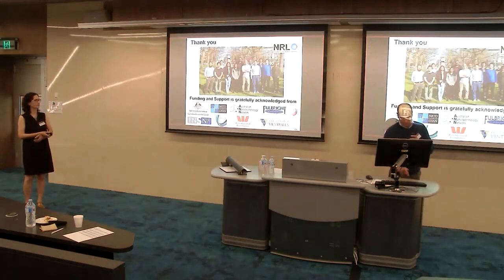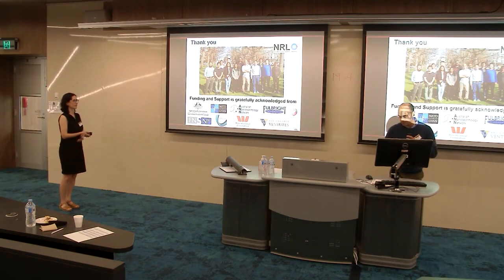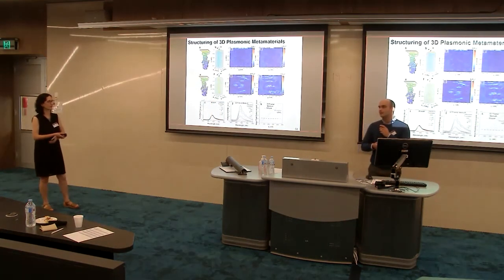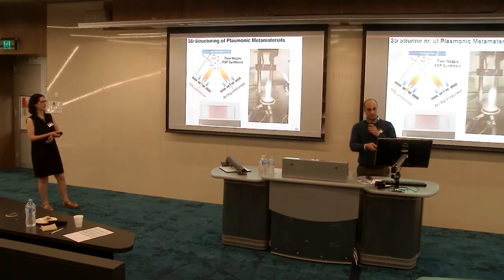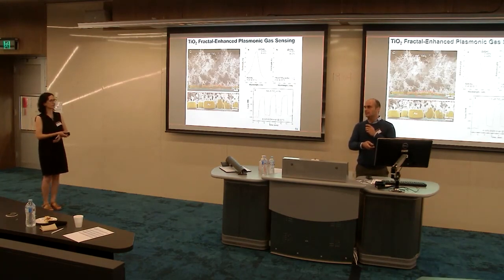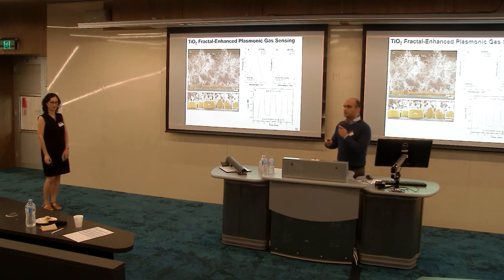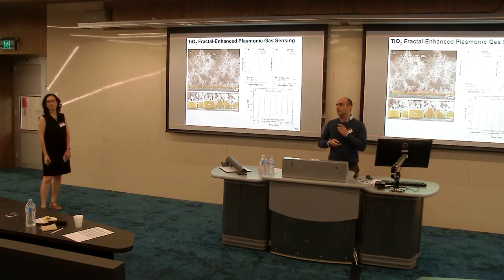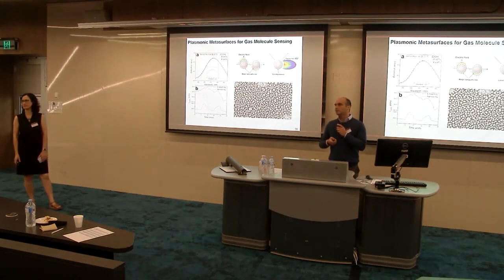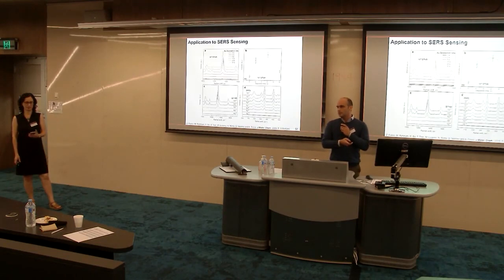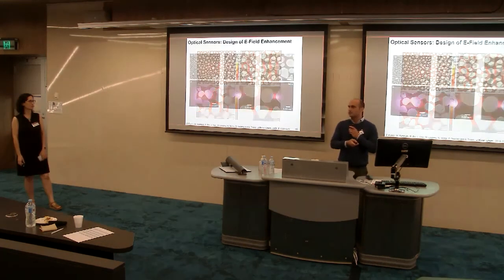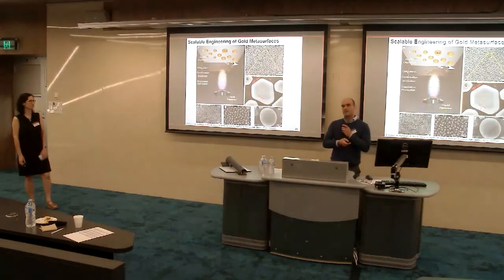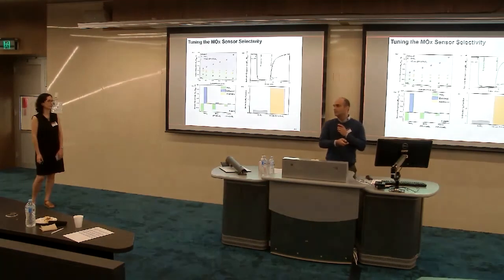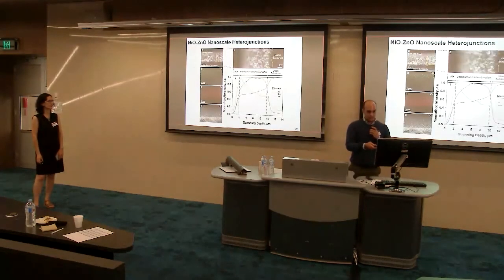Well, there are a few options. First of all, you don't always have to use high temperature. I was trying to get to that slide, but you can use light instead of temperature to activate the reaction. So we are able to perform this under UV light, for example, at room temperature or slightly higher temperature. You can put a UV LED, for example, and use that. If instead you'd prefer to use temperature, which has some advantages sometimes, then you can have a micro hot plate heater, like the one I was showing in one of the first slides.